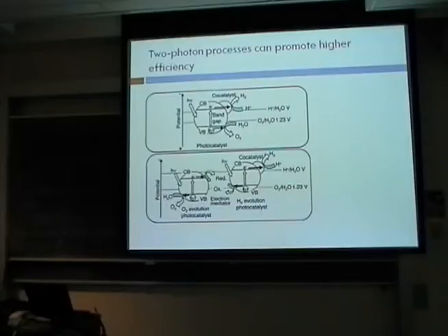And so what is being explored a lot for use instead is to have basically two kinds of catalyst particles that are floating around in your bath of water that you're shining light on. One of those particles is utilizing the holes and reacting with water to make oxygen. Then the electron that's created from the photoexcitation process reacts with some intermediate species, some oxidant-reductant that you're cycling through, that is basically acting like a co-catalyst, that there's no net production or consumption of, but it's just acting as an electron shuttle between the catalyst particles.